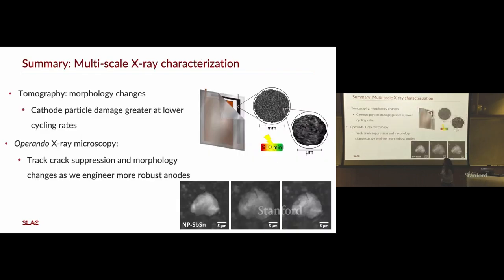So in summary, we looked at tomography on the cathode and used the morphology changes, the volume size, and the sphericity as a proxy for particle damage, and related that to the capacity on the cathode as you fast cycled it, the loss of capacity.